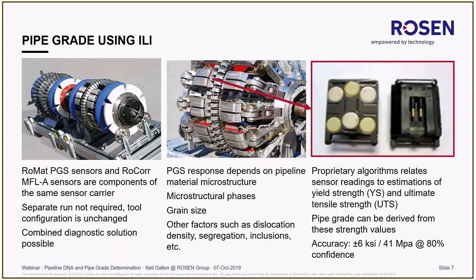Within our development, ROSEN has developed proprietary algorithms which relate the sensor reading to the actual strength of the pipe. These are fairly complicated and they do need a lot of inputs and calculations, but it gives us an estimation of the yield strength and the ultimate tensile strength from which we can derive the appropriate pipe grade. The accuracy that we can get from this is plus or minus 6 KSI at an 80% confidence level following the calibration digs. So we can tell you what grade it is to plus or minus 6 KSI with an 80% confidence.